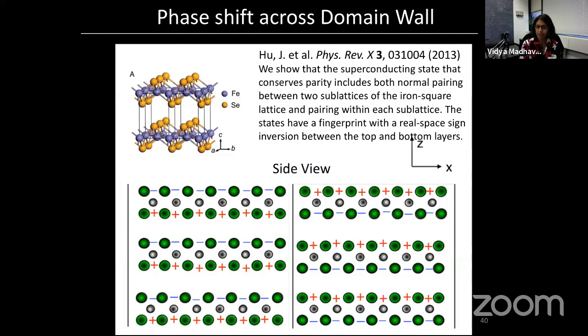And this is an amazing material. It turns out that there is a nice crystallographic way to get a pi phase shift in iron selenium tellurium. This work was done by Jiangping Hu in 2013. He showed that for many of these iron-type superconductors, if you do a theoretical study where you consider both nearest neighbor and next nearest neighbor pairing, then you can show that there is a sort of parity shift between the top and the bottom layers of this material.